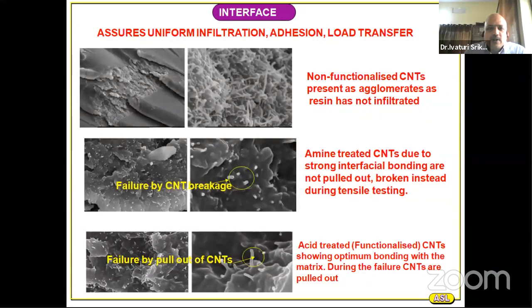Same thing, a non-functionalized matrix here, same images again shown. Again, the type of functionalization also makes a lot of difference. If you functionalize with acid groups, they will form a very weak bond with the matrix. If you functionalize with amine groups, they will react with epoxy and form a strong bond. So what kind of failure pattern do you want? If the nanotube is to be pulled out during the failure, then you have to generate a functional group which will give weak interface bonding. If you want the nanotube to be broken and the energy to be absorbed by breaking of the nanotube, then you have to go for an amine functionalization of the nanotube.